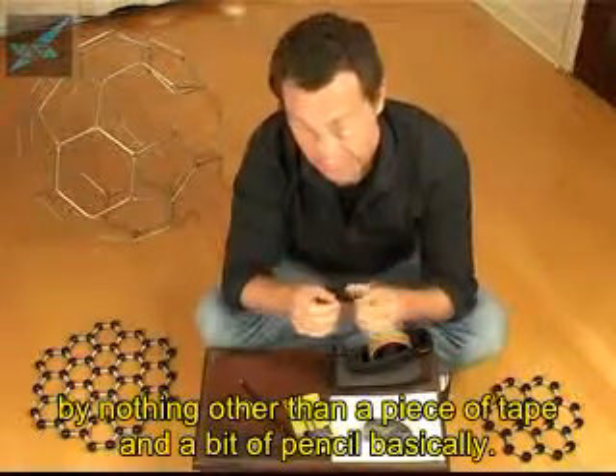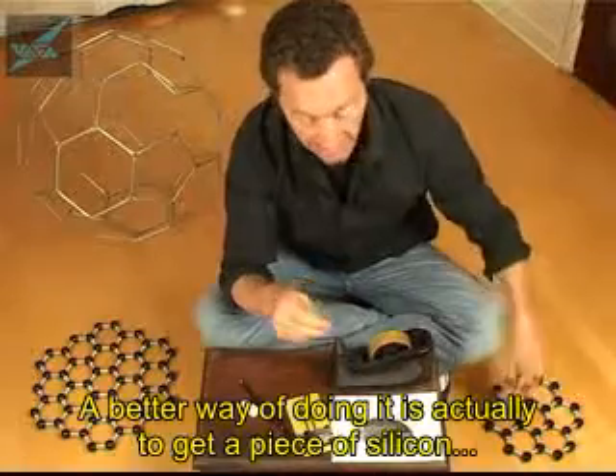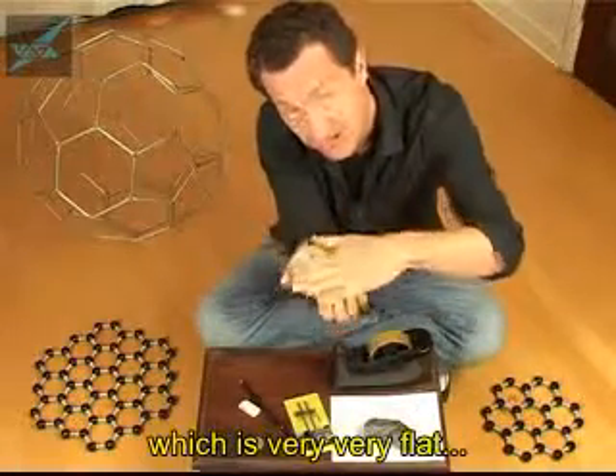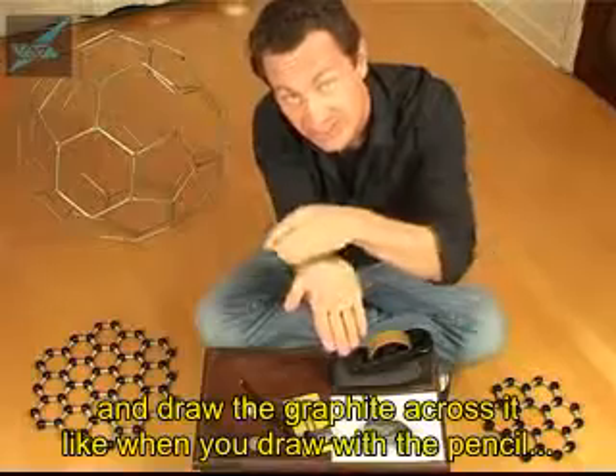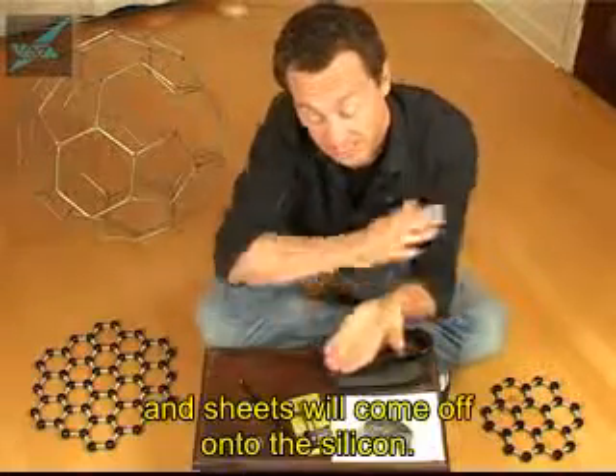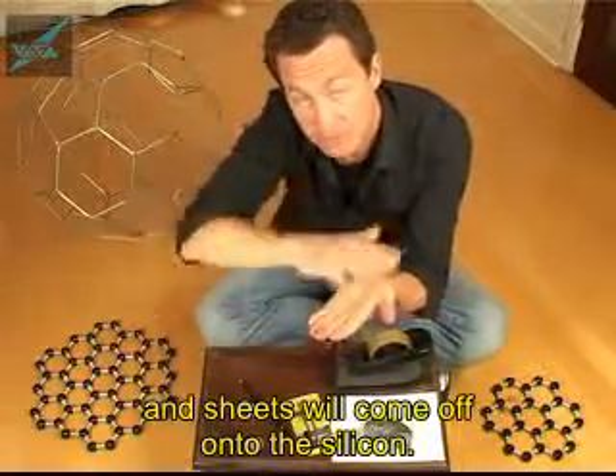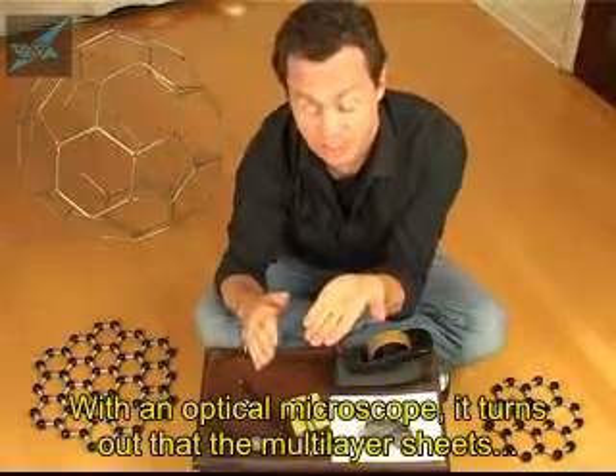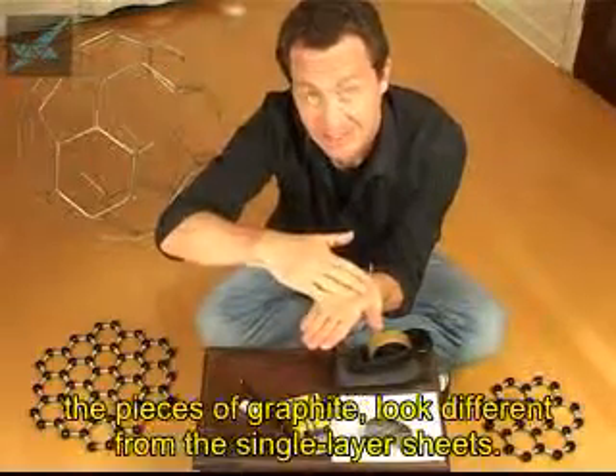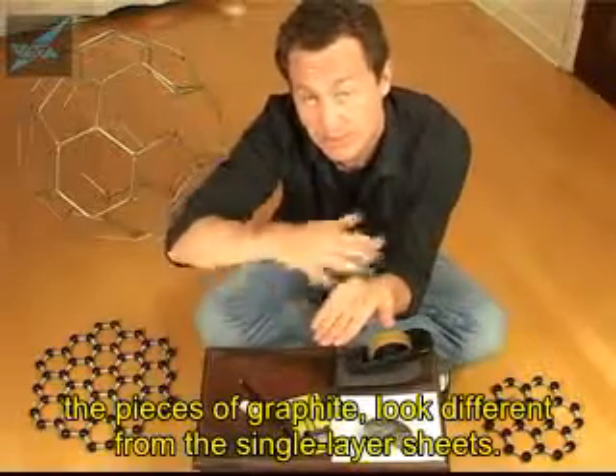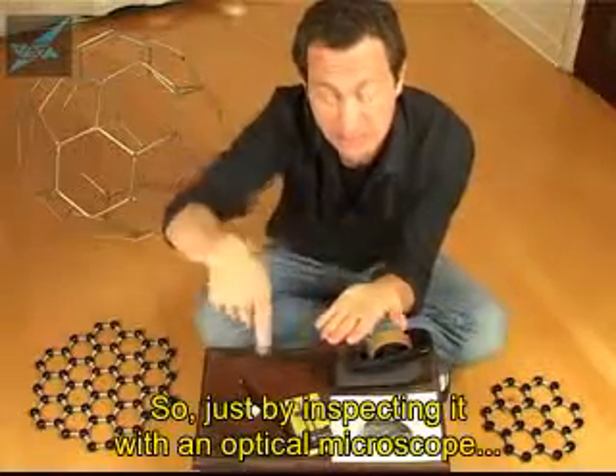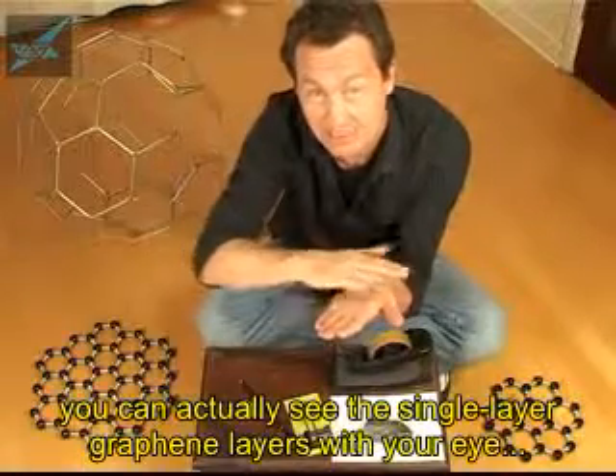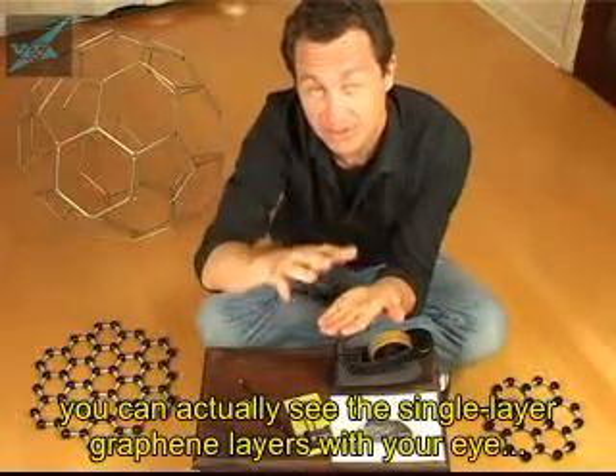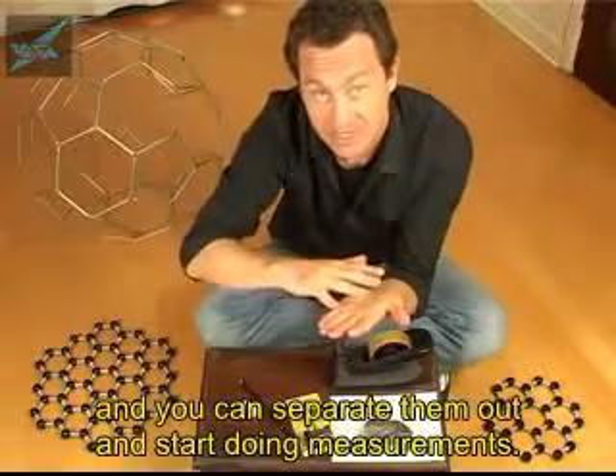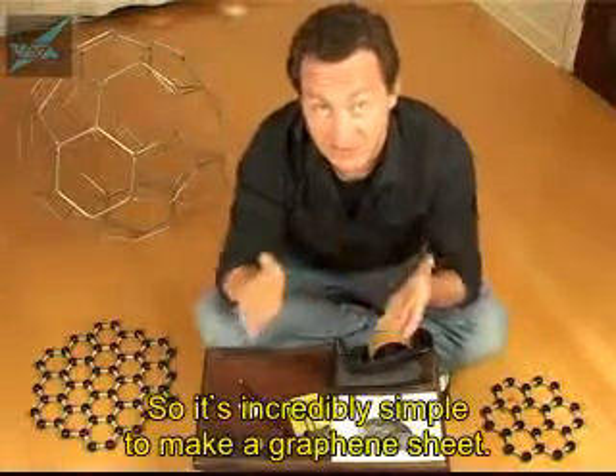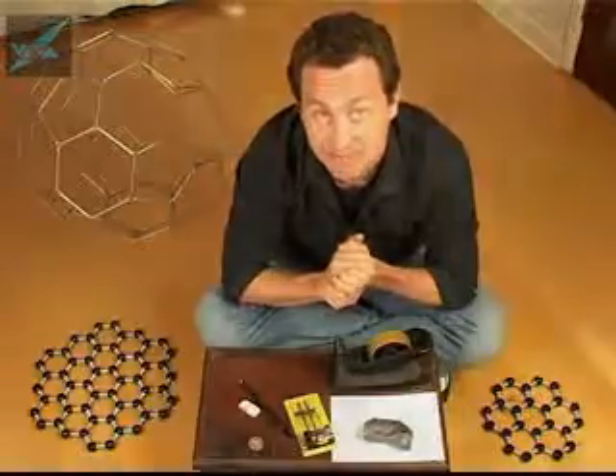A better way of doing it is actually to get a piece of silicon, which is very, very flat, and draw the graphite across it, just like when you draw with a pencil. And sheets will come off onto the silicon. And with an optical microscope, it turns out that the multi-layer sheets, the pieces of graphite, look different from the single layer sheets. And so just by inspecting it with an optical microscope, you can actually see the single layer graphene layers with your eye. And then you can obviously separate them out and start doing measurements. So it's incredibly simple to make a graphene sheet.